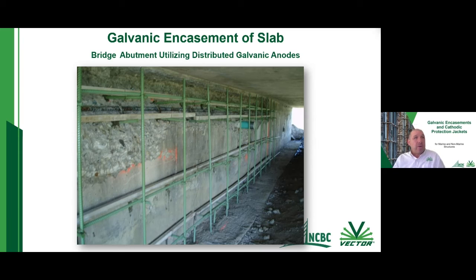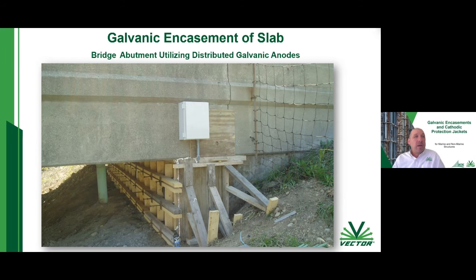We want those anodes that you see installed there. We want these anodes to protect the epoxy coated steel and the reinforcing steel within the original abutment as well. So then they came in, they put their formwork up, and you can see there's a junction box here. That's how we're able to get all the readings from these anodes.